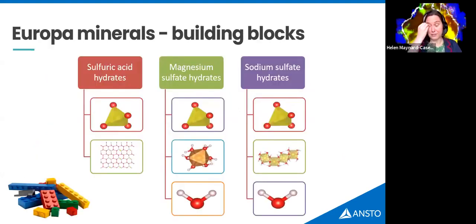We've taken this to the next level and begun to look at some of the other components. So magnesium sulfate hydrates and sodium sulfate hydrates are both meant to be quite important on the surface as well. And these are thought to be coming from the ocean below and onto the top of the ice. I've started to break this down in terms of Lego bricks, in terms of how the crystal structures are put together, especially with magnesium sulfate hydrates. They have this very octahedral unit going on there, with the magnesium bonded to the six water molecules, and that's a feature.